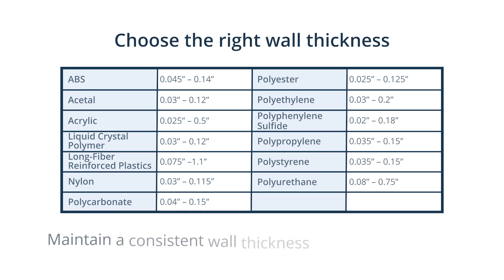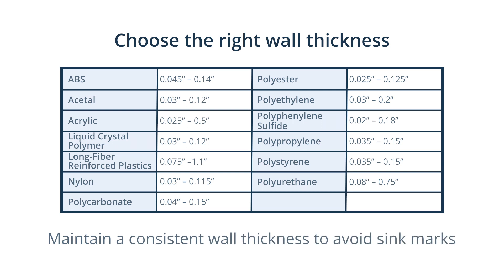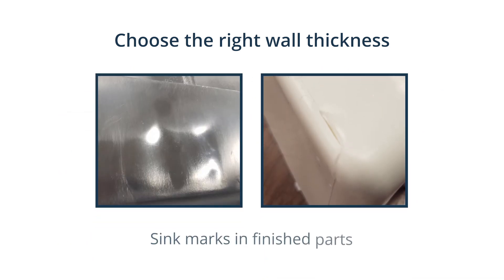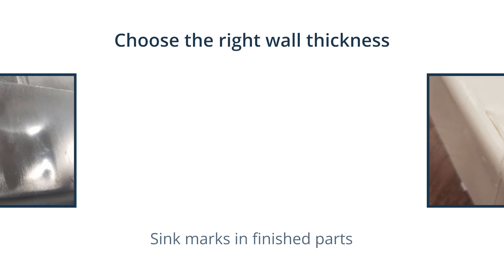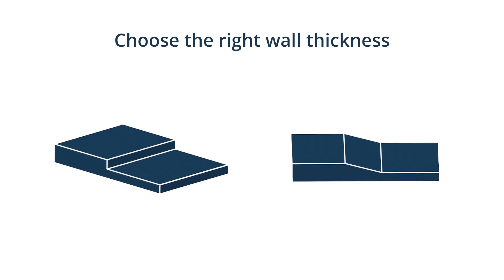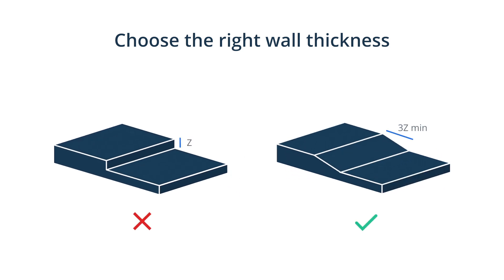Unlike CNC machined parts, plastic injection moulded parts benefit from a consistent wall thickness. If a part is thicker in one section than another, a sink mark will appear at that location. Non-uniform wall thicknesses also lead to warping, as these walls cool and shrink at different rates. If you require a non-uniform thickness, the change in thickness should not exceed 15% of the nominal wall thickness and should always have a smooth or tapered transition to achieve a high quality part.